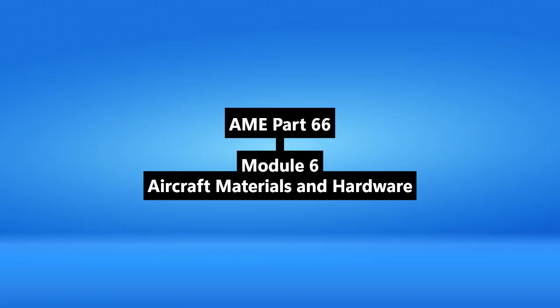Ah, good point. What about pre-pregs, the ones with resin already in them? Pre-pregs need careful handling. Often stored frozen, need thawing, precise cutting, correct ply orientation, then laid up, vacuum bagged, cured under heat, usually in an autoclave or oven. Vacuum bagging seems important. Crucial for consolidation, removing trapped air between layers. Yeah. Ensures a strong, void-free repair. So lots of precise steps.